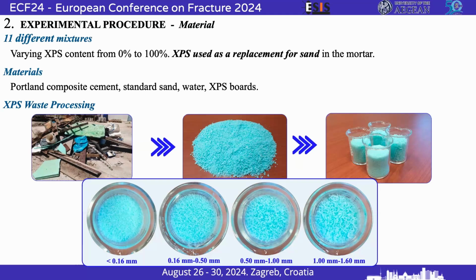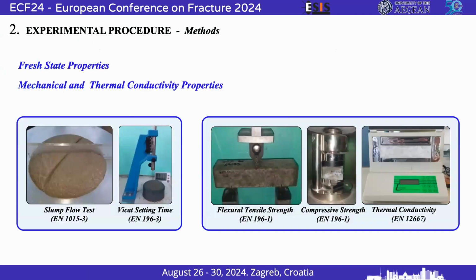We had a mortar material, and our mortar material was composed of Portland cement, standard sand, our XPS waste, and water. We studied the fresh state properties of the material and the mechanical properties. For the fresh state properties, we did two different tests: the slump flow test, to study the flowability, and the Vicat test in order to determine the setting time of the material, so how much time it takes for the material to harden. And also we tested its compressive strength, the flexural strength of the material, and the thermal conductivity according to all of these different standards that you see in this slide.